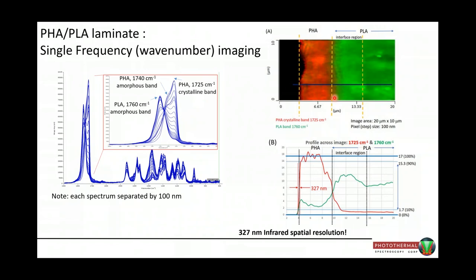And if we go across the boundary, you can see when we hit the boundary at the very edge, we're achieving what is apparently about 327 nanometer spatial resolution. But in fact, at the boundary, we don't get a sharp boundary. That means there's sort of an interaction between the PLA and the PHA. And Asao will go into a lot more detail, including how to make sense of how the spectra change over the boundary and learn about the mixing of those two components.